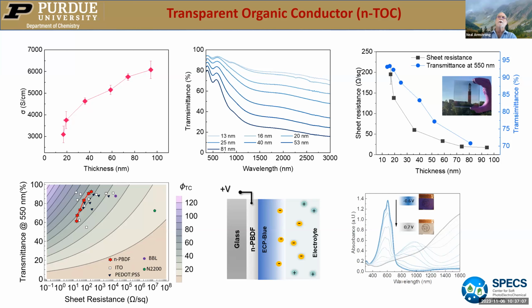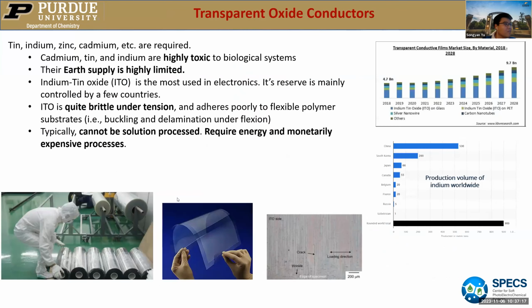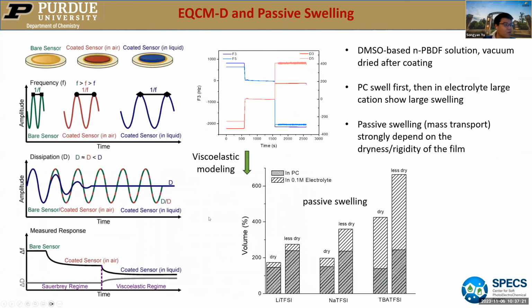So when you do the de-doping, do you think you're expelling protons or taking up anions? Yes, it had an ion exchange effect. I didn't mention this one because it can be seen from the swelling process. Take it in electrolyte, it's passive swelling. When we dip in PC, it swells first, then we have the electrolyte, so there's also a volume increase. The volume is actually calculated from mass increase. If there's a mass increase, that definitely means a larger mass cation comes into the polymer to replace the proton, because the conductivity keeps relatively stable. So there's a huge ion exchange effect.